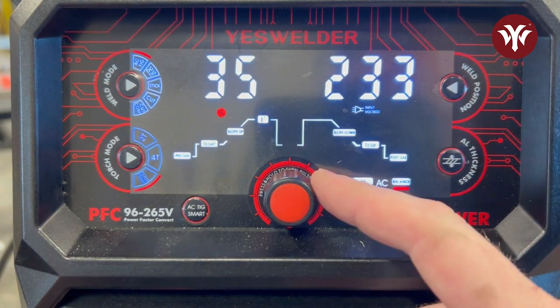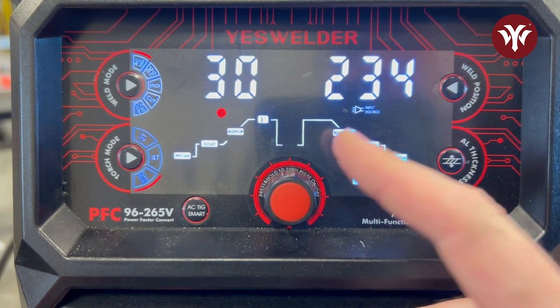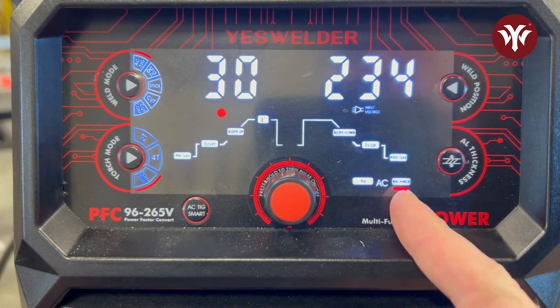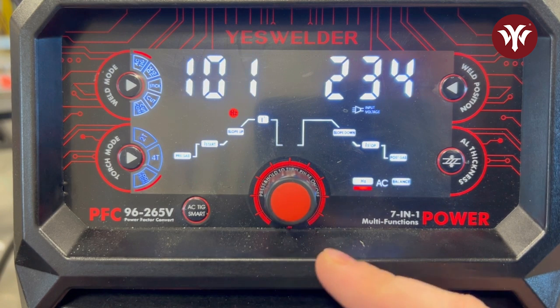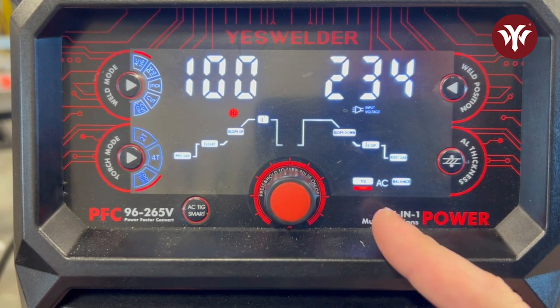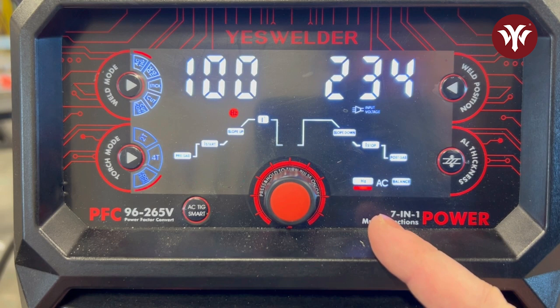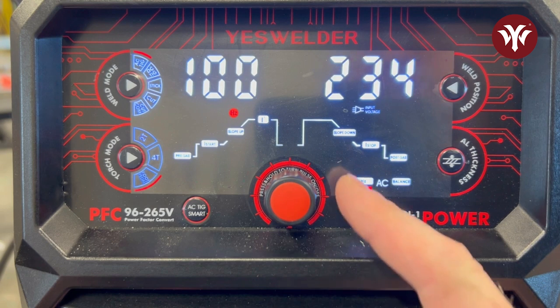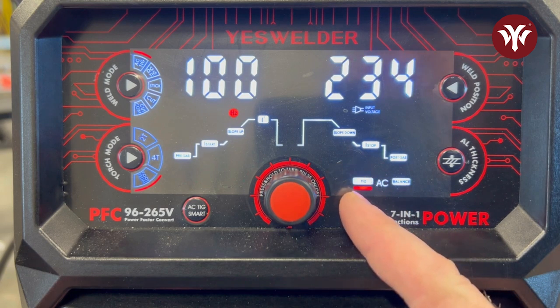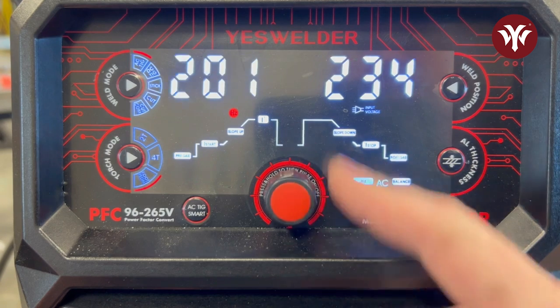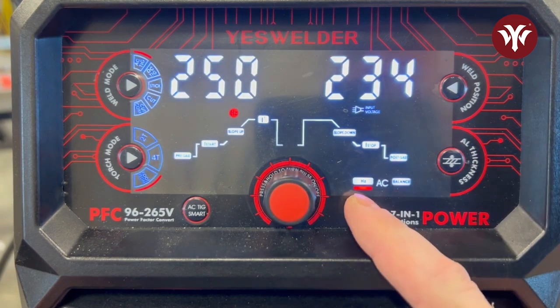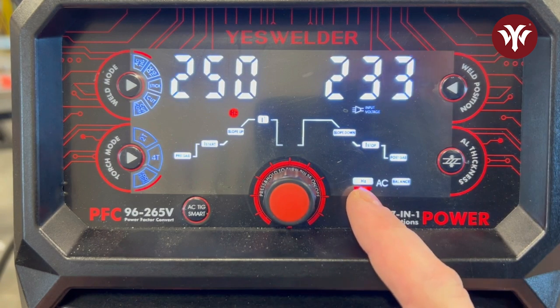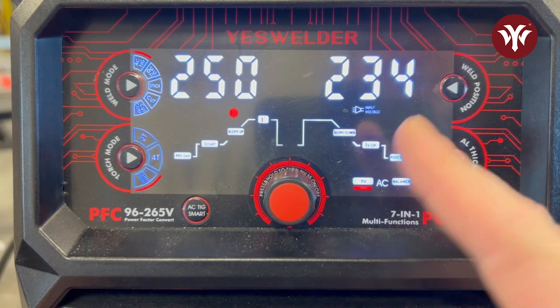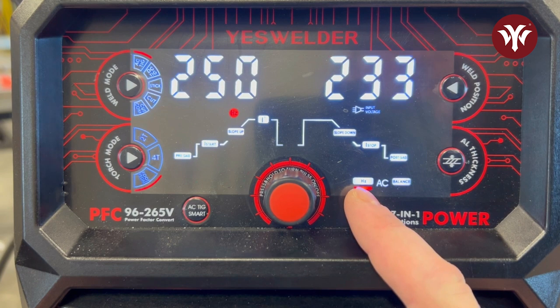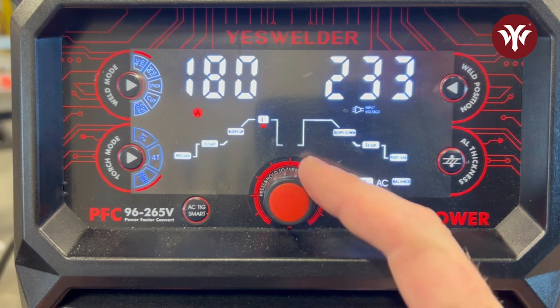Balance, as I said, set to 35. Let's turn that down to 30%. I think that will be a good start for the clean aluminum we're welding with. And frequency, we'll set to 100. As I said before, 85 to 100 hertz is a really good place to be welding with your typical aluminums. It can go all the way up to 250 hertz, which is absolutely wild. That is a very high frequency. I've never welded at 250 hertz, but I guess there's a need to do it.